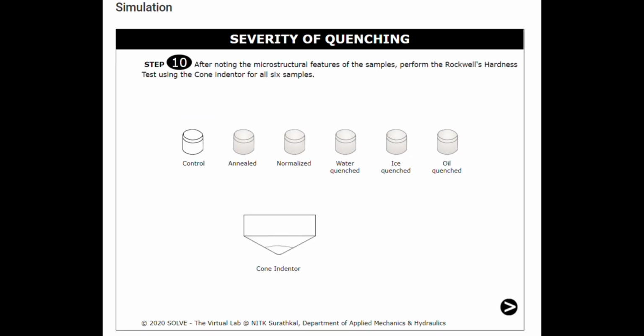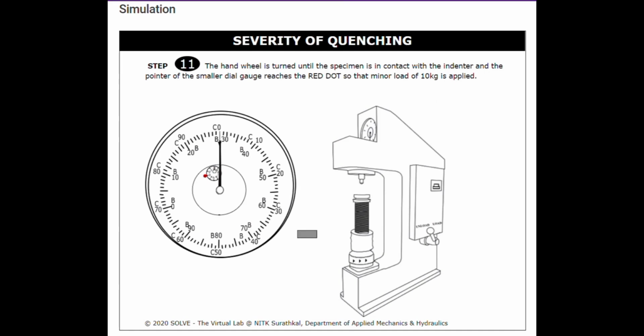In step 10, after noting all the microstructural features of the sample, we have to perform the Rockwell hardness test using cone indenter for all the 6 samples. In step 11, the handwheel is turned until the specimen is in contact with the indenter and the pointer of the smaller dial gauge reaches the red dot, so that the minor load of 10 kg is applied.